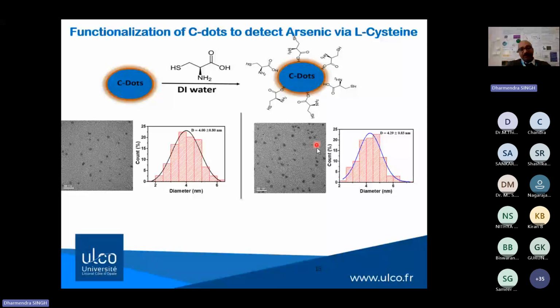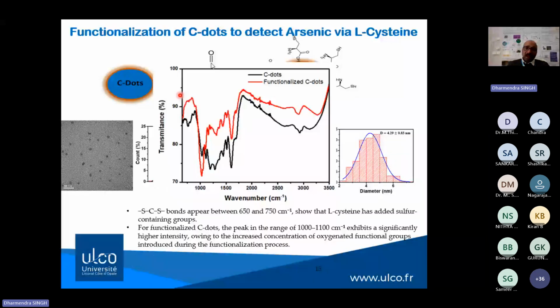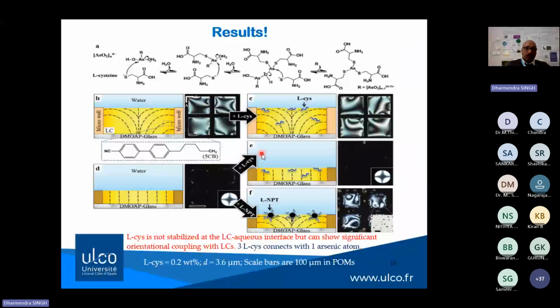You can see here the effective diameter of the synthesized carbon dot was around 4 nanometers, and when it was functionalized by L-cysteine, the effective diameter became 4.29 nanometers. This shows that something is bound over the surface of the carbon dot. Later we also did FTIR to prove that the functionalization was done successfully. Here is the mechanism of how we achieved the selective detection.